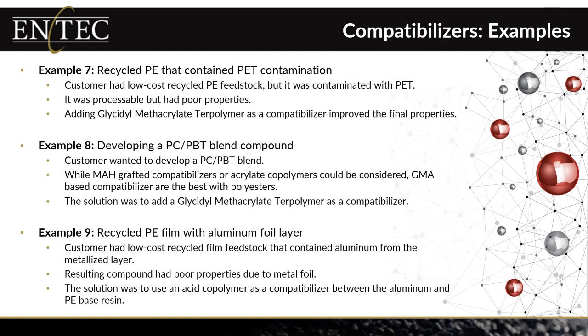And the last example, recycled polyethylene film that contained aluminum foil contamination. Needless to say, if you've got aluminum in your polyethylene, it's not going to be compatible. It's going to be a contaminant. It's going to be a cause of failure in a molded product. So in order to compatibilize that, here's an example where the acid copolymer would probably outperform a maleic anhydride grafted material to use as a compatibilizer, because those acid copolymers love aluminum and they have very, very high bond strength to that aluminum, compatibilizing your product, and you're able to make a better performing compound.